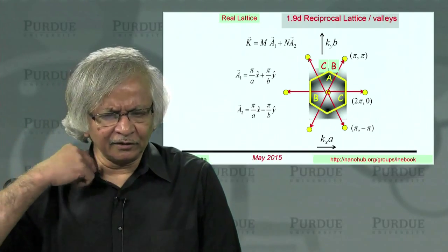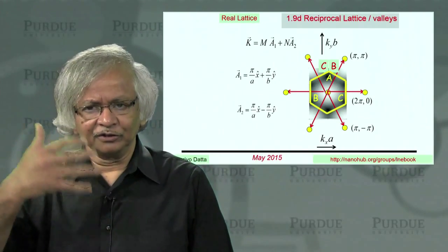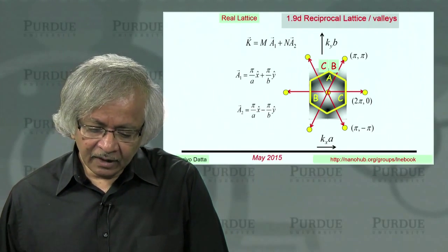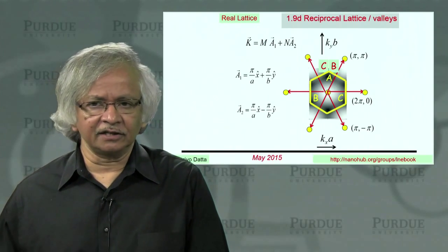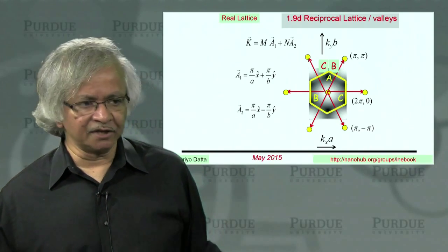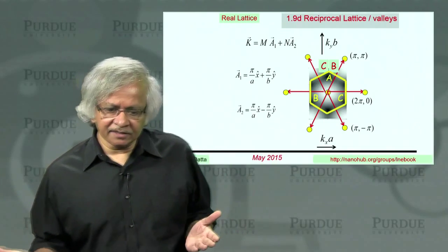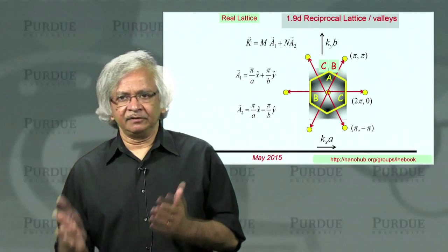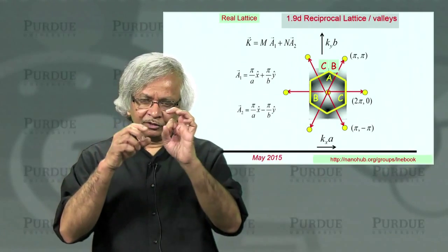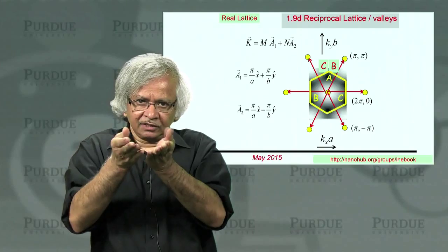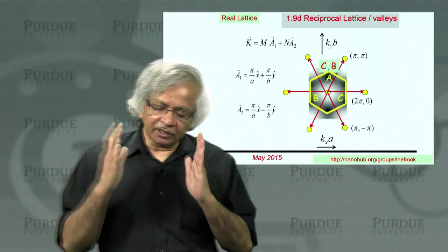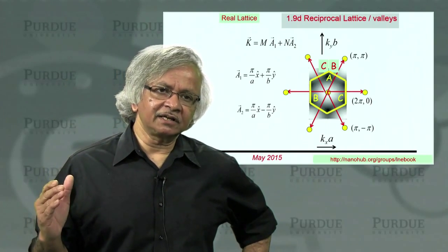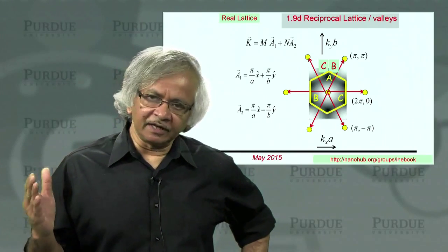You can see it was a relatively mathematical argument. We had to go through this reciprocal lattice, construct things in Fourier space and so on. But the number of valleys has a very direct consequence in terms of measurable quantities, which people have done. When people look at ballistic conductors, ballistic graphene or ballistic carbon nanotube, which is like graphene rolled up into like a straw, and look at the ballistic conductance, as you know, usually the ballistic resistance is supposed to be roughly 12.5 kilo ohms.